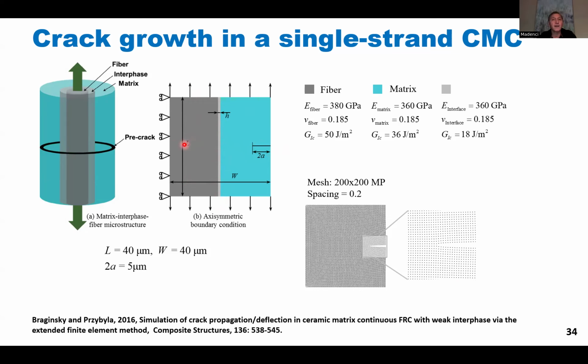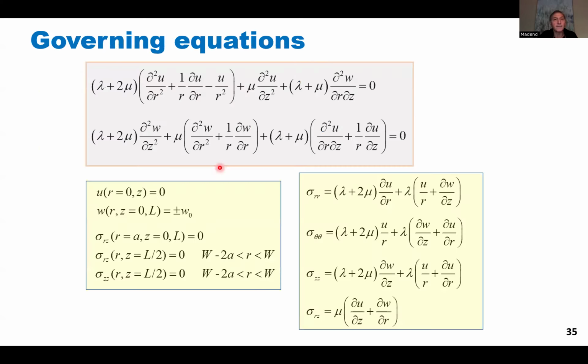So you have the matrix, the fiber, and then the interface. You have a pre-existing crack, and then you pull it from the top and the bottom. What's going to happen is this crack is going to propagate, go through, and then hopefully deflect, right? So that's the problem. And these are the governing equations we have. We're using the axisymmetric set of governing equations here. It's my displacement equilibrium equation, both in R and Z directions. And these are my boundary conditions. This is the stress-strain relationship, okay? The material properties, lambda and mu, are Lamé's material constants.